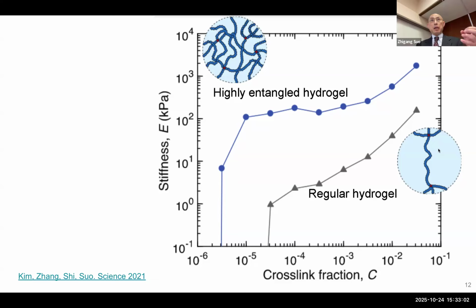This measurement is done after swelling. You can see the stiffness is very small if your crosslink fraction is really low. This crosslink fraction is the number of crosslinkers divided by the number of monomers. It's pretty much how many monomers are in between the crosslinks. If you put too few crosslinks, the network is not well prepared. The chains are not really linked together, so your modulus is very low.